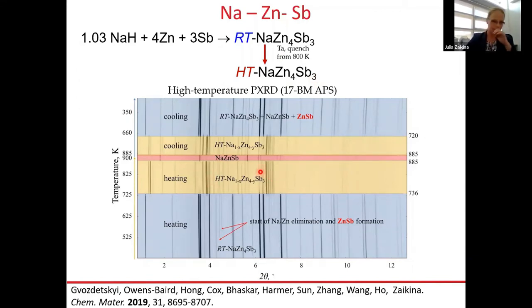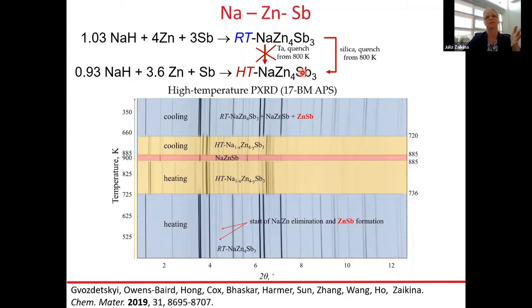So we've tried various routes, and this was until we performed our reaction in the silica. And the reason for it to work is that there is a side reaction between sodium metal and silica, which allows us to access the sodium deficient composition. And after we determined the crystal structure of that high temperature phase by using single crystal X-ray diffraction, we realized that sodium and zinc deficiency are both needed for the successful synthesis of this high temperature phase.